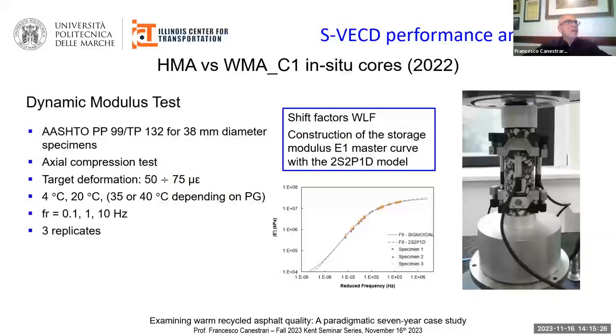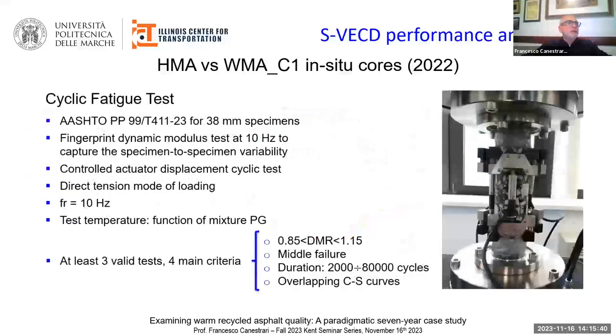Once obtained the small size specimens, first we performed the dynamic modulus test according to AASHTO standards to obtain the storage modulus master curves with the 2S2P1D model. Then the small size specimens were also used for cyclic fatigue tests according to AASHTO standards to obtain the pseudo stiffness curves as a function of the damage parameter S.